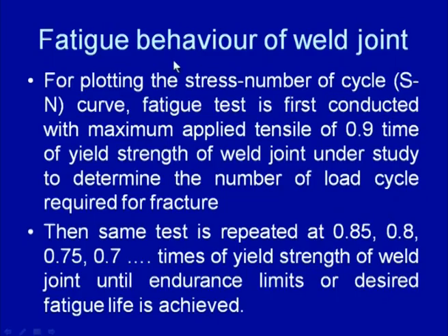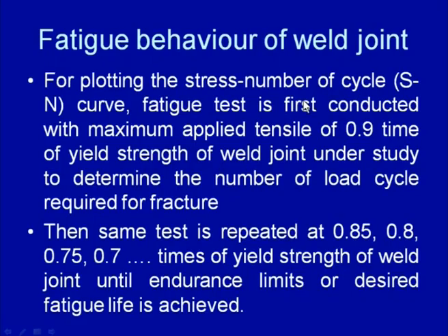So, for conducting the fatigue test, suitable kinds of stresses are developed and applied onto the specimen as per requirement. It is common to conduct a rotary bending test, which develops tensile and compressive stresses in each load cycle, while axial stresses are also used, where either 0 to tension or tension to tension stresses are applied. Apart from the rotary test, axial loading is commonly used for the fatigue test. In the case of axial loading, we first conduct the tensile test of the specimen, so that we know the yield strength and ultimate strength of the material.